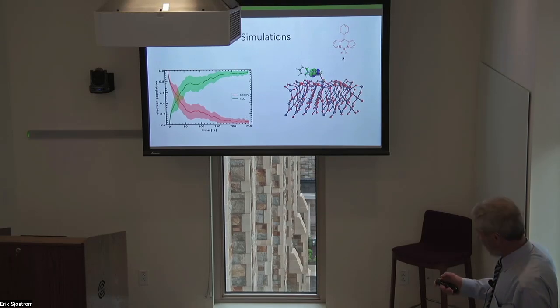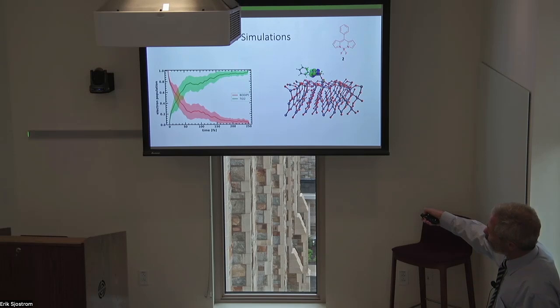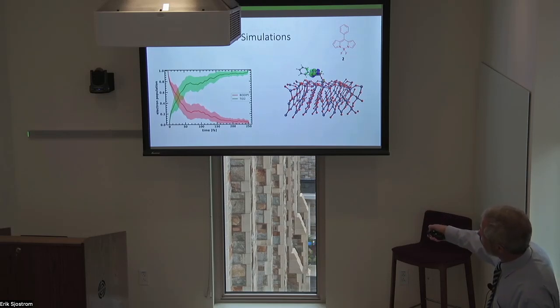And this is something that we've been able to also simulate. Victor Batista and one of his postdocs simulated the injection reaction using a quantum dynamics simulation. What he does is he puts the electron in the excited state of the Brudvig molecule bound on the surface of titanium dioxide. Here's the electron in the conduction band. And then he simulates the transfer of that electron, which then disappears from the Brudvig orbital and appears in the titanium oxide surface.